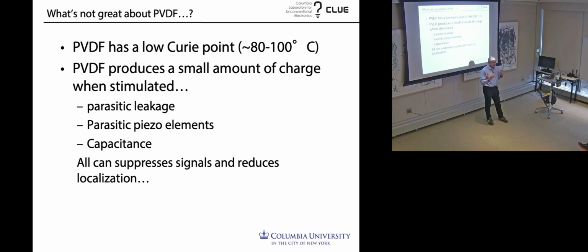And so PVDF, if it's heated, depending on how you crystallize it, to somewhere around 90 degrees, maybe 95 degrees, it unfortunately undergoes a solid phase recrystallization in which you lose its piezoelectric characters. That really limits the thermal budget with which we can process it.